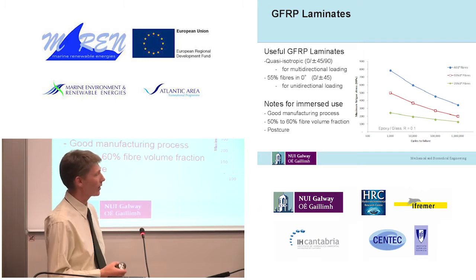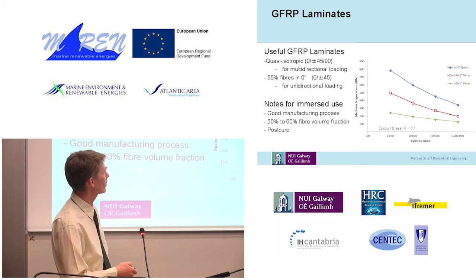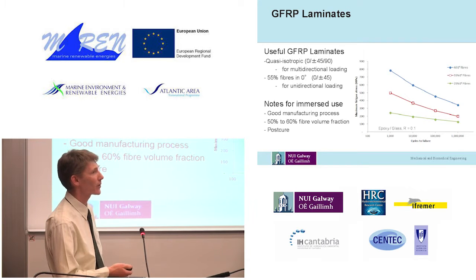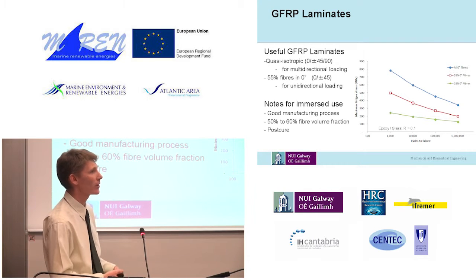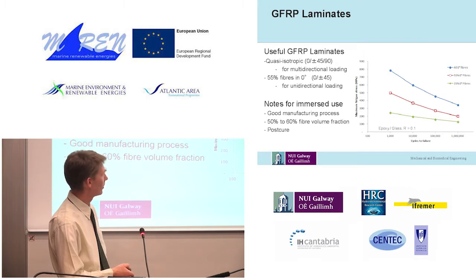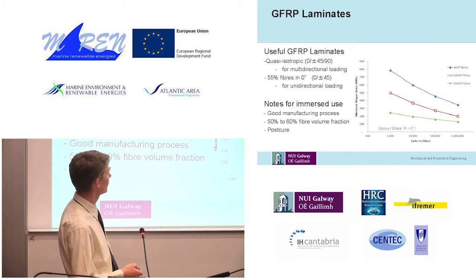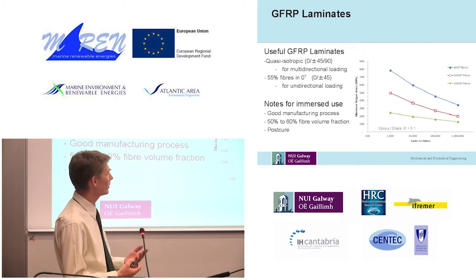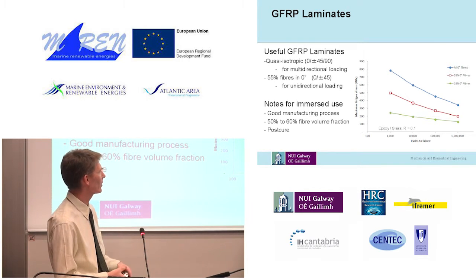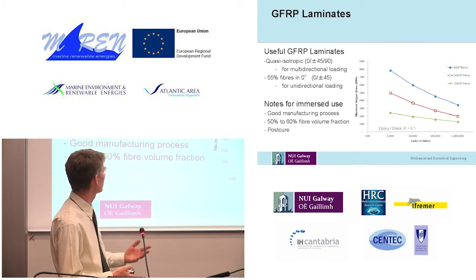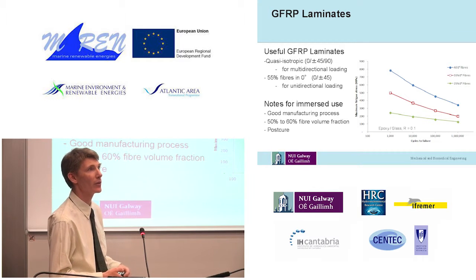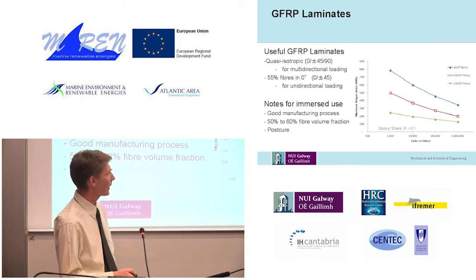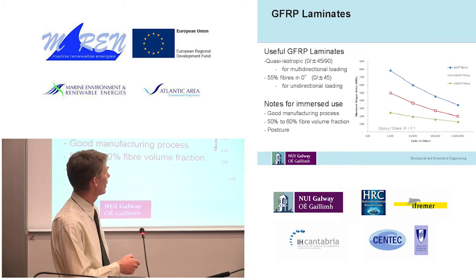So the next useful laminate to talk about is a laminate where we align about 55% of the fibres in the direction of the nominal load, and the rest of the fibres are usually oriented at plus or minus 45 degrees to that. That material is useful for unidirectional loading, where you know the direction of the load, but maybe there's some multi-axiality or a little bit of uncertainty about where it's going to go. A typical application for this that most of you would know would be wind turbine blades. And this material has a fatigue strength of between 500 MPa and 200 MPa.